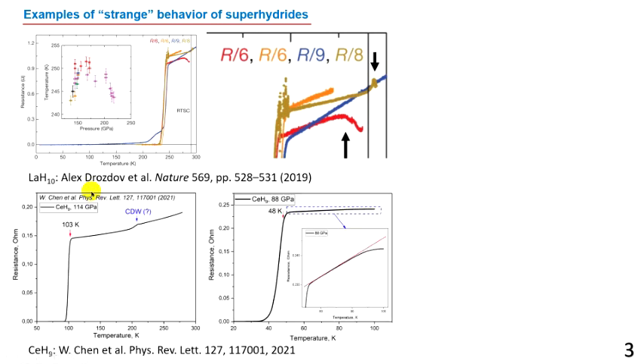In the next publication, Wuhao Chen from Jilin University investigated the behavior of cerium H9 at 114 GPa. The curves were published in Physical Review Letters in 2021, and you can see there is a wave upturn feature here, which looks like a charge density wave. And definitely it deviates from the behavior of a normal metal. Another example is the same compound at 88 GPa. The resistance transition is significantly lower, but we see that there is strong deviation from the Bloch-Grüneisen fit, from the Fermi-liquid model again, and even flattening of the resistance curve at temperature around 100 kelvins.